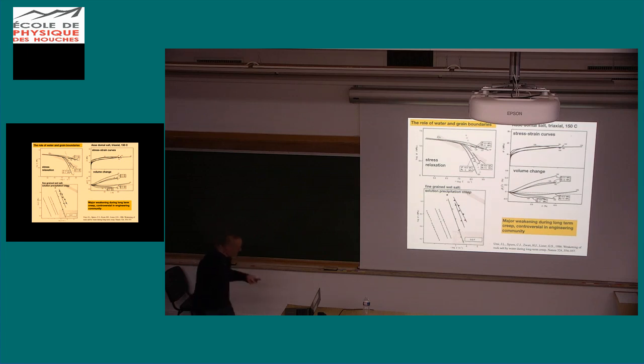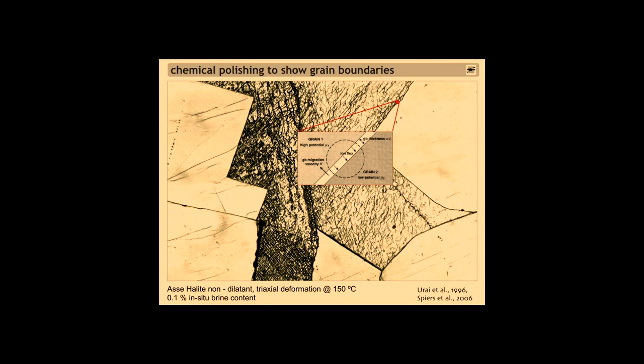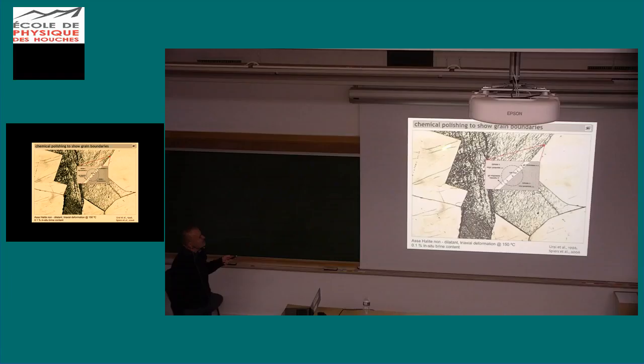But what we found is that there is a very easy and simple technique to look at the microstructure of rock salt. What you do is you polish the samples, and then you etch the surface with a slightly undersaturated sodium chloride solution, which basically dissolves the surface.